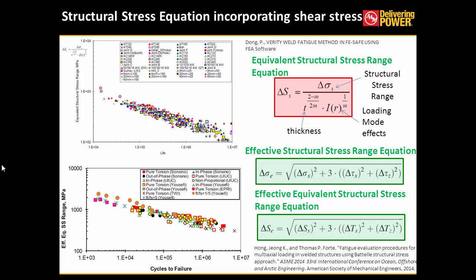But that does not mean that it can be applied to all the cases. Let's say there is a case of torsionally dominated loading, or maybe even a pure torsion. In those cases, we might need to include the shear components. So from the distortion energy theory hypothesis, we have the von Mises form of the structural stress, which is shown as the effective structural stress range equation, which includes the in-plane and the transverse shear components. And by including the thickness and the loading effects, we are able to calculate the effective equivalent structural stress range equation. So on the left chart below, most of the cases are pure torsion and torsionally dominated cases, where we were able to obtain a very thin band of data.